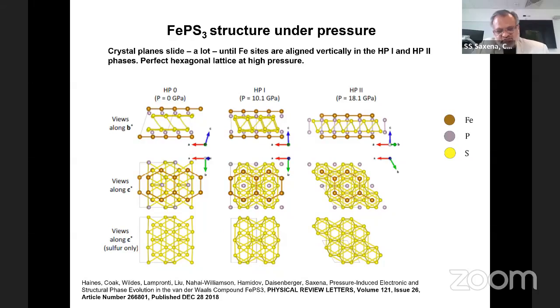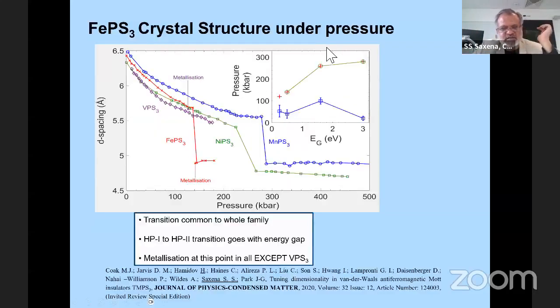So when you apply pressure, not to the single layer, but to the bulk single crystal or powder, what you see is that with the application of small pressure, the layers slide, and then at the highest pressures they resettle and rebond. So effectively, you take a 2D material and you apply pressure to it, and you start to see it becoming more 3D at the highest pressures, which is kind of interesting in its own right. This work was published in 2018, the structural part. And if you want to follow that, looking at the d-spacing, this is what you see.